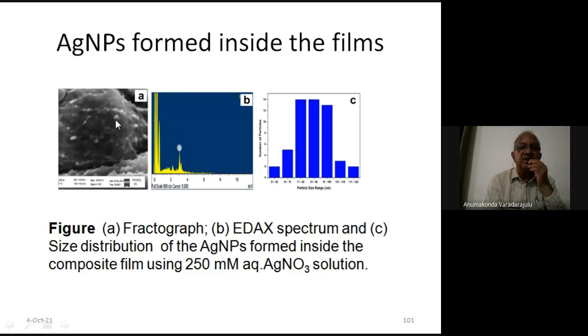So these are the spherical nanoparticles. And how to prove that they belong to silver? For that, we go for the EDX, which is the attachment to this SEM itself. This is nothing but the energy dispersive spectrum. Actually, different metals will have different energies. So this particular peak shown by the EDX spectrum corresponds to the silver metal.